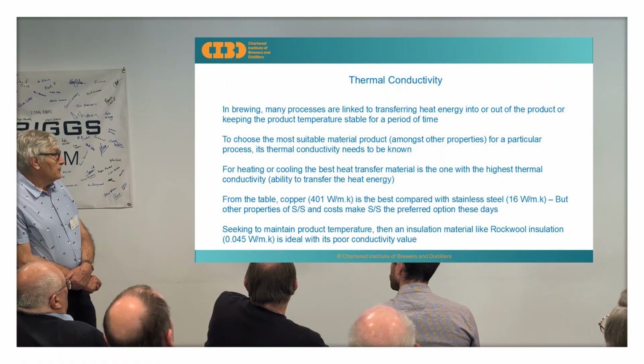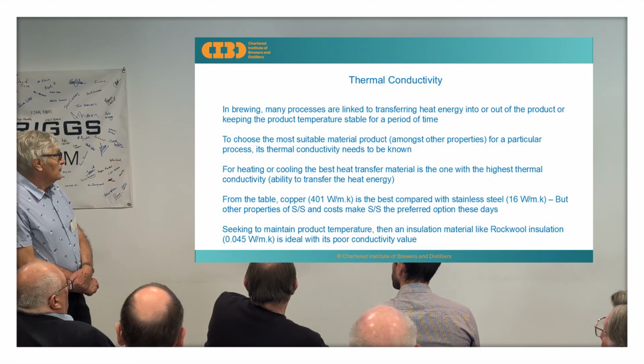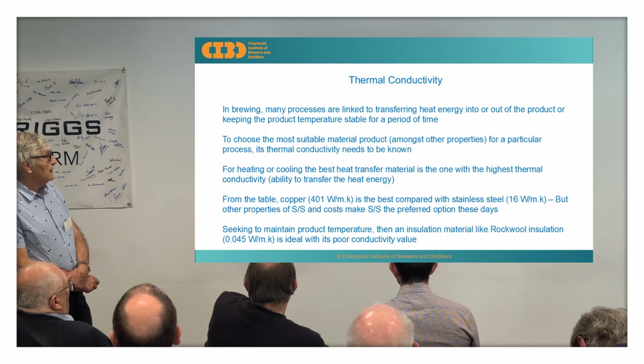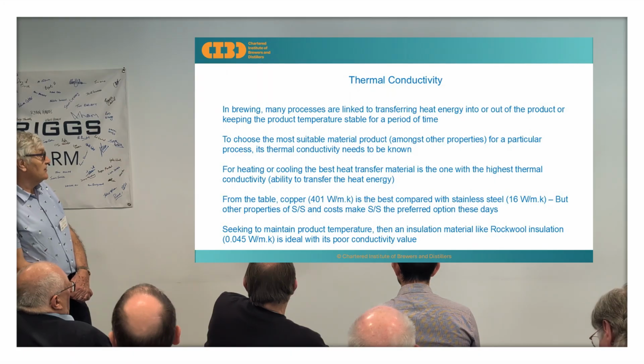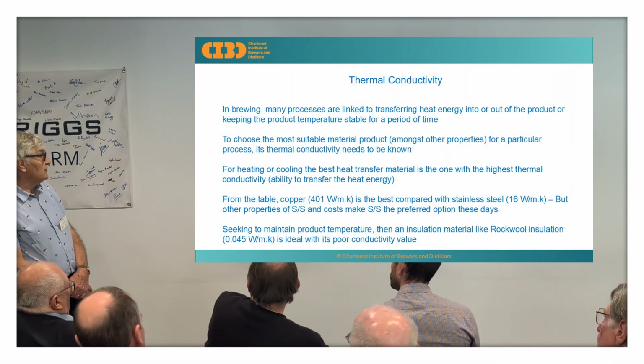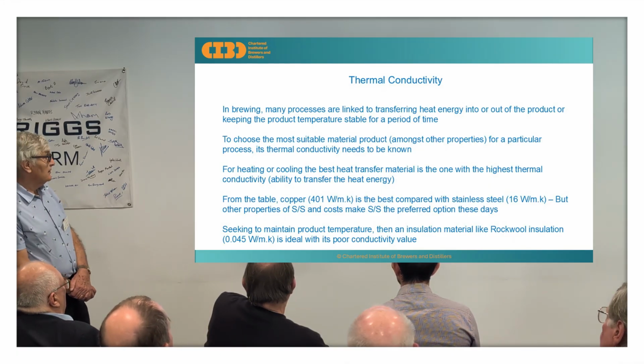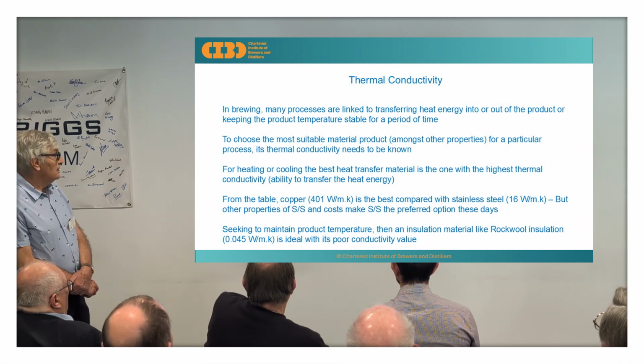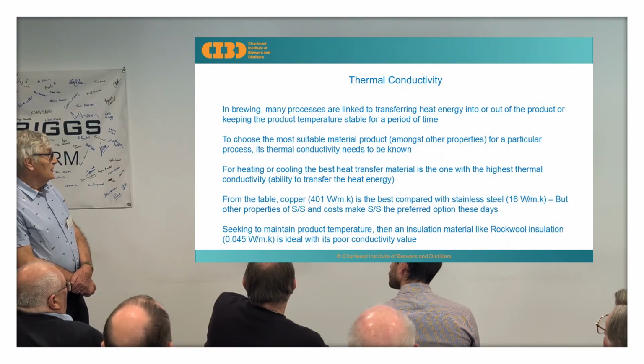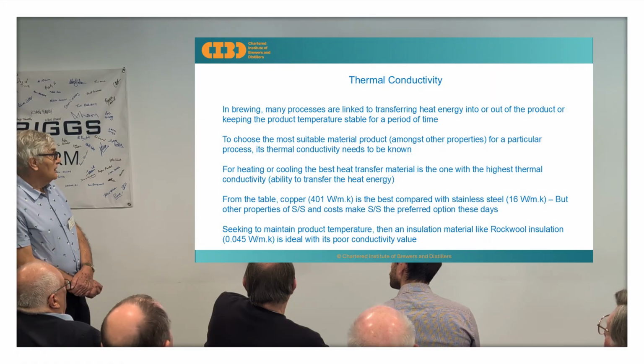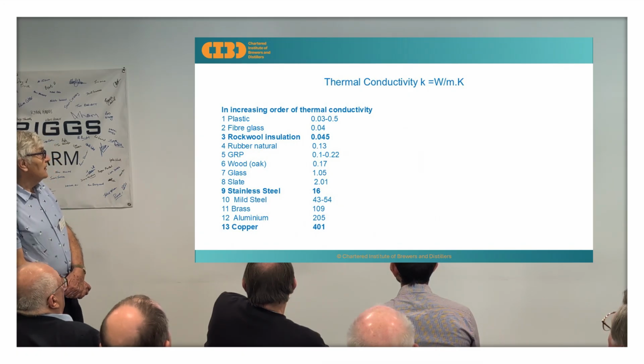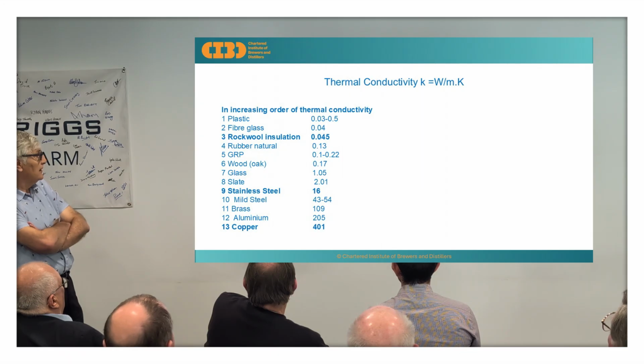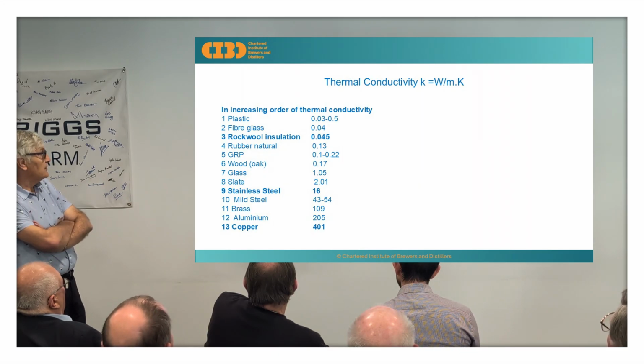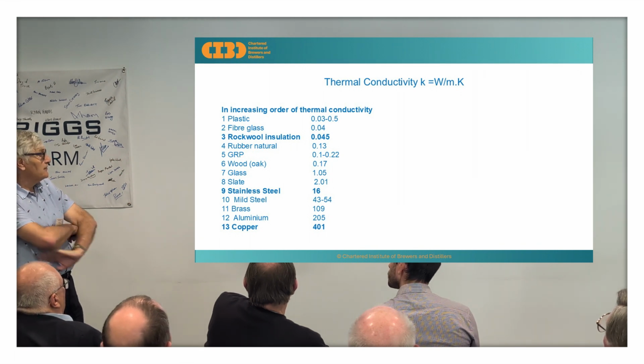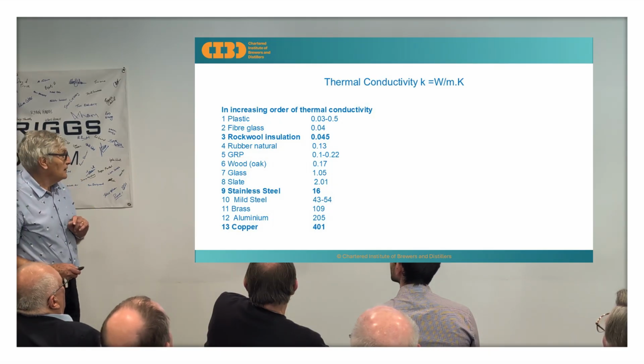From the table you'll see on the next slide, copper has a thermal conductivity of 400 watts per meter per Kelvin, and is brilliant compared to stainless steel, which has just got 16. As I said earlier, it is other properties that stainless steel excels at that make it preferred these days. And just as a throwaway, some products like rock-wool insulation have an incredibly poor conductivity, and it's used as an insulator. So there you go, there's this thermal conductivity table with copper heading the lead, stainless steel way down at 16, and mild steel a little better, but it's one of the trade-off areas, and it's not as bad as it could be. You'll see why in a minute.